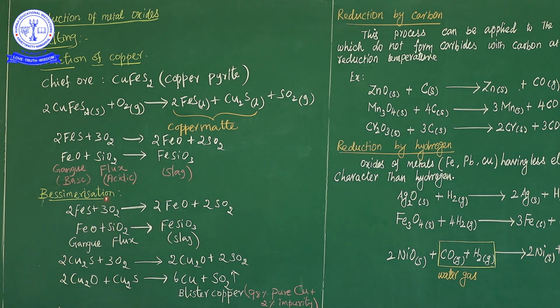So the second one, the matte which consists of cuprous sulfide also. So iron sulfide is removed as a slag by passing hot air. So the cuprous sulfide is also oxidized. So both are oxidized. The matte which consists of ferrous sulfide and cuprous sulfide, both are oxidized by passing the hot air. Ferrous sulfide is oxidized to form ferrous oxide and reacts with the silica, it gives a slag. So the cuprous sulfide is also oxidized to form cuprous oxide. Then the sulfur is removed as sulfur dioxide gas.